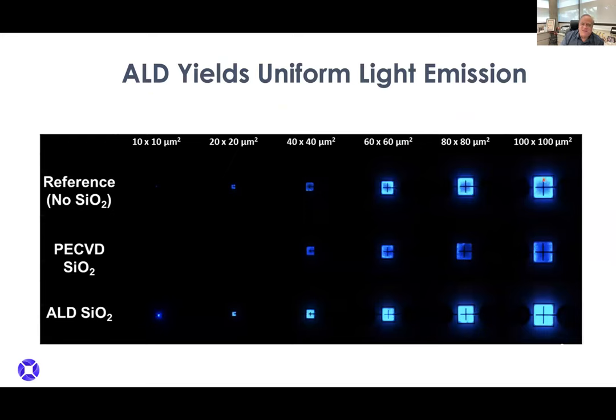But I think it's just better to show you how important atomic layer deposition is to the impact on the device. So the first row here shows you the traditional LED fabrication process. As people went from 100 by 100 to 20 microns, you could see the brightness went down a lot. So people said, well, I don't think it's going to be possible to make a display with a resolution of below 10 by 10 microns. And they tried what's called plasma enhanced chemical vapor deposition to put down SiO2 to passivate. And that actually made things worse.